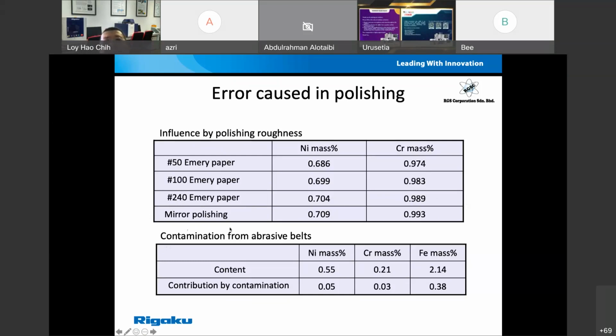Besides that, the polishing with emery papers will also contribute some contamination. Especially from your emery papers, it will give a certain level of contamination into your results. For instance, nickel is actually 0.05% contributed by the abrasive belts, chromium is about 0.03, and Fe is 0.38.